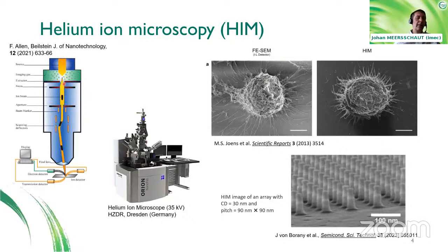And the ions are, with a special technique, you have a very narrow source, or a very point-like source of helium ions, and they can be directed towards the sample very much like an electron microscope. The advantage of this technique is that it is very surface sensitive and not so much damaging to, for example, organic materials.